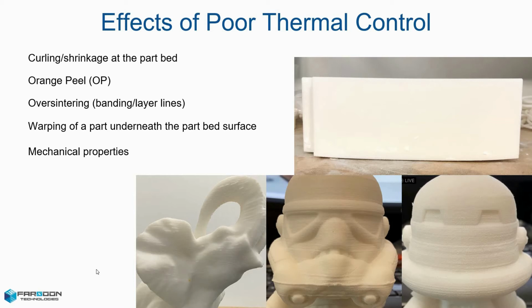Next, we have over-sintering. This is sometimes referred to as banding or layer lines. This is seen horizontally on a part surface, similar to orange peel, and is caused when radiant heat fuses unsintered material to the sintered part surface. This is often accompanied by a harder than normal build part cake. This also indicates an excessive amount of heat energy, either coming from the part heater or, if the part or parts are located on the outside edges, the cylinder heaters. To resolve these types of issues, lowering the part bed or cylinder temperature heaters is recommended.